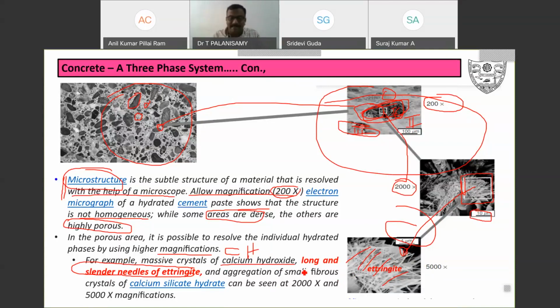Suppose you look at a scanning electron microscope, the SEM or TEM or whatever it may be, and see any structure like a needle. A needle like this may represent ettringite. How it forms, I will tell you. And aggregations of small fibers of crystals of calcium silicate hydrates can be seen only at 2000 and 5000 magnifications. So simply what I am trying to say is that there is a lot of heterogeneity, a lot of non-homogeneity in this concrete. You can see it only through microcharacterization of the concrete.